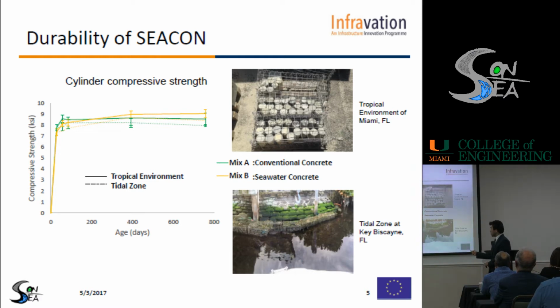So still, even for the tidal zone, where the samples were exposed, the compressive strength after 2 years and also 1 year was higher for mix B. So these are the results.